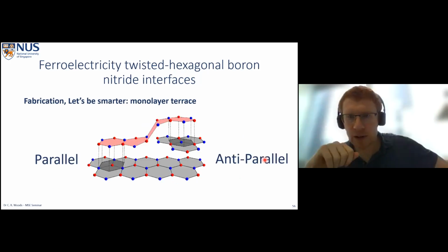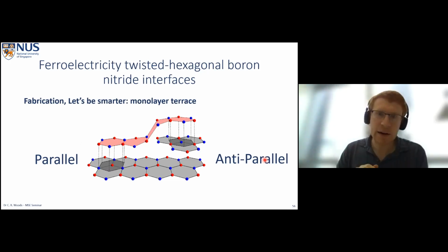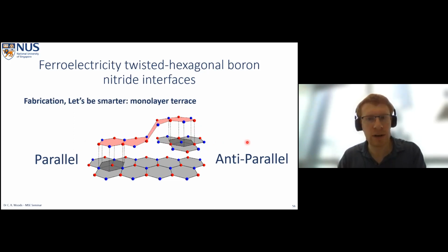So if I put a boron nitride on top of a monolayer terrace in a substrate boron nitride, then on one side of the terrace, I'll have, say, the anti-parallel stacking configurations. And on the other side of the terrace, I would have the parallel stacking configurations, because the difference in the monolayer terrace is already this 180-degree twist. So we can do those two things. We can create superlattice samples where we can probe the different stacking configurations for each configuration, but we can also put our boron nitride across a monolayer step so that we can see both parallel and anti-parallel stacking configurations all in one sample.